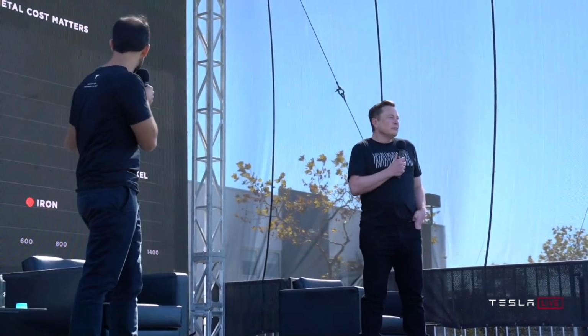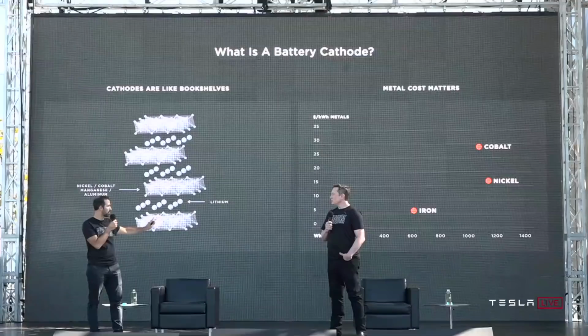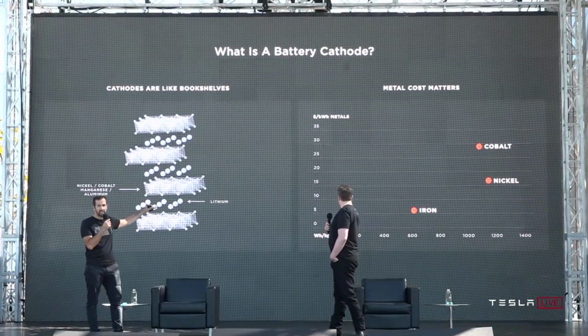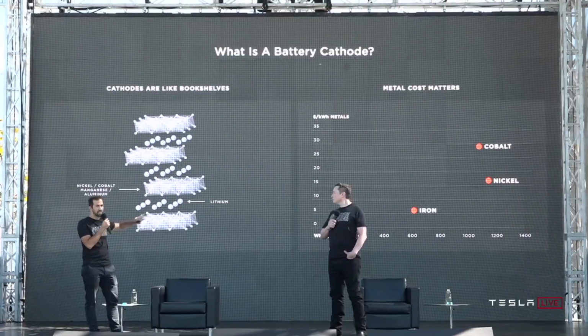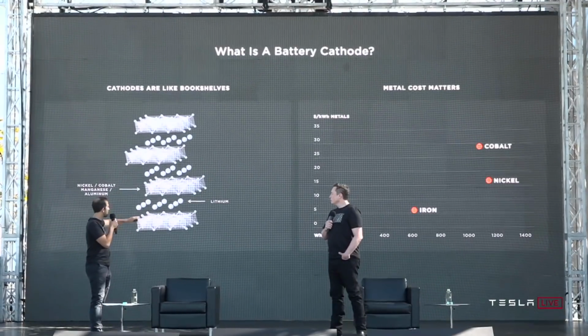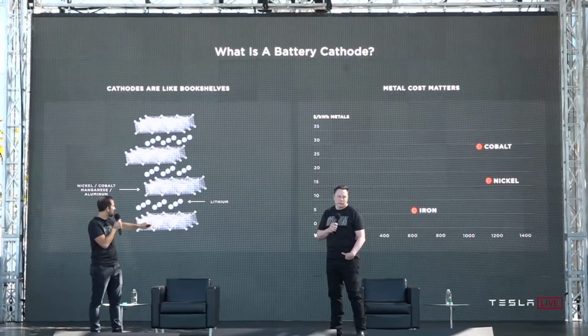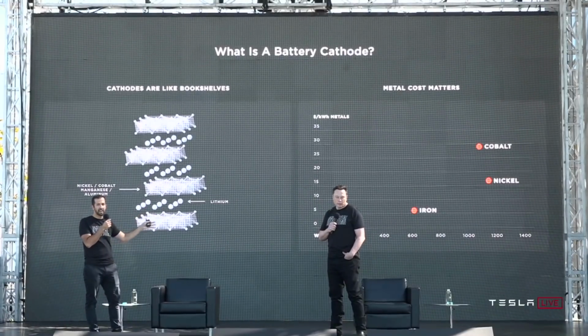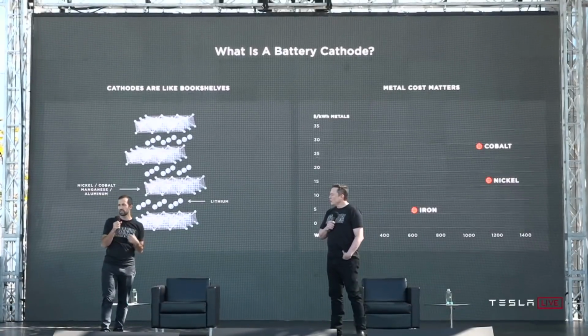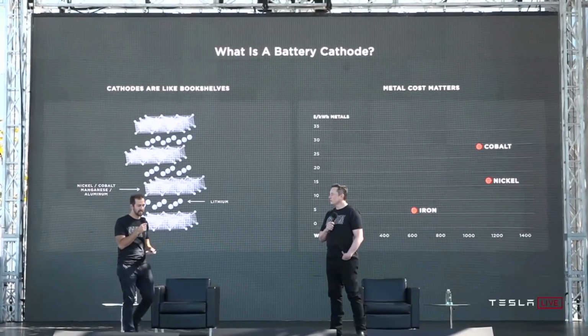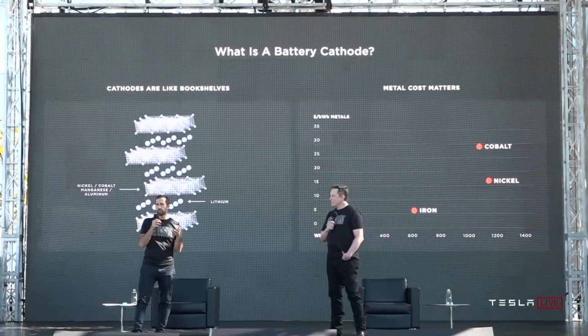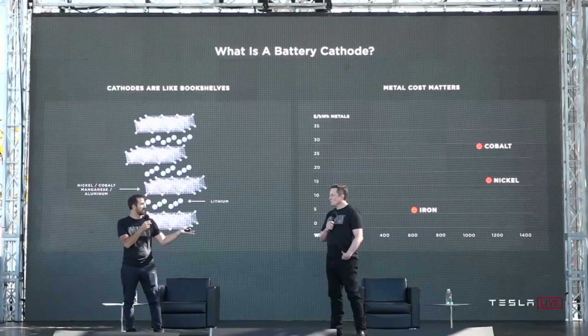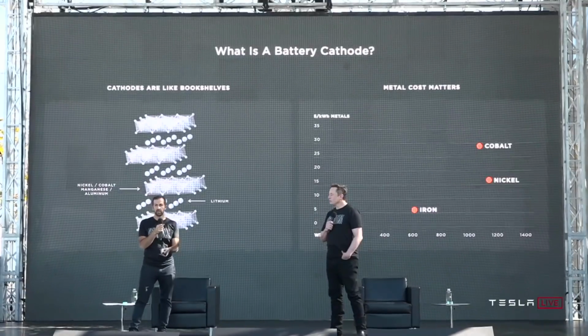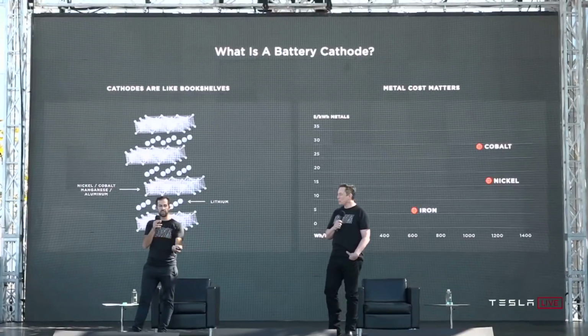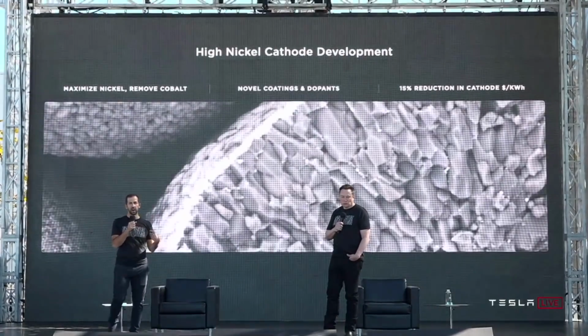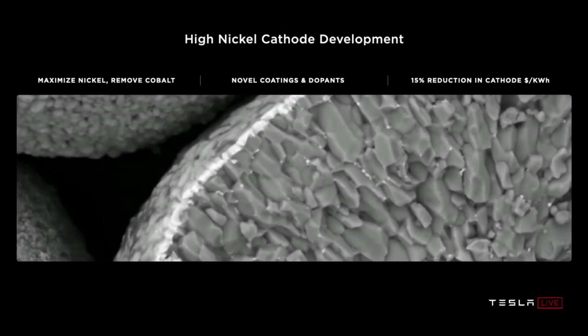The thing to consider is just fundamentally what the metals are capable of, and that's what we have on the chart here. Dollar per kilowatt hour cathode of just the metal, using just LME, London Metal Exchange prices, versus the energy density of just the cathode. And you can see nickel is the cheapest and the highest energy density, and that's why increasing nickel is a goal of ours and really everybody's in the battery industry. But one of the reasons why cobalt is even used at all is because it is a very stable bookshelf. And the challenge with going to pure nickel is stabilizing that bookshelf with only nickel. And that's what we've been working on with our high nickel cathode development, which has 0 cobalt in it.